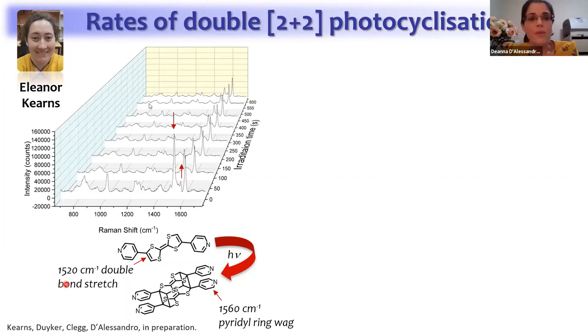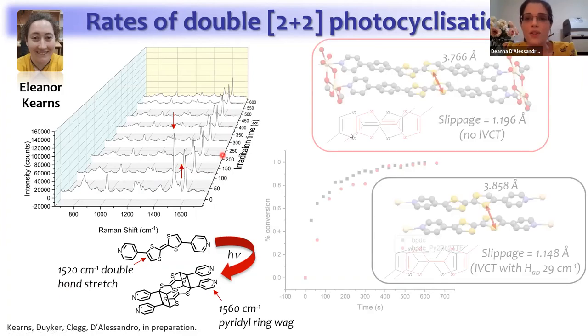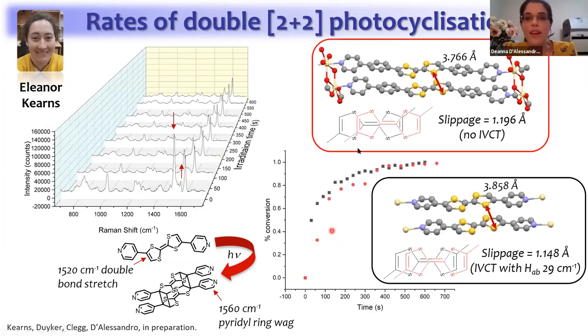And so here we use this light irradiated Raman experiment to good effect. And I just wanted to show you the comparison of the parent system, if you like, with the extended linker. So what is interesting here, if we follow the percent conversion, is that over time, the conversion rates are very similar.